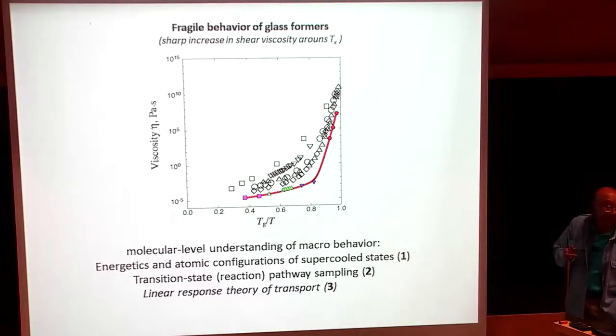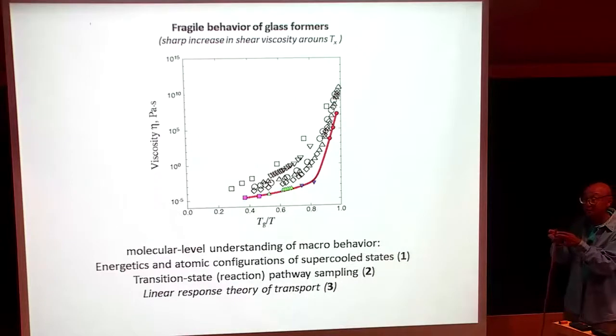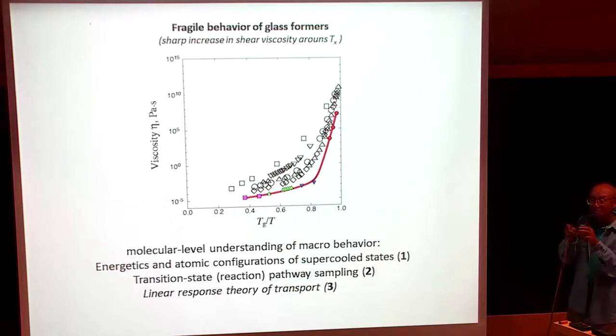People who do scattering experiments will say, well, I don't necessarily measure g(r), although you can get it out of the data. I don't measure viscosity. I measure a diffraction pattern. I can take a liquid and measure its diffraction pattern, and I see rings, the so-called Debye-Scherrer rings. If I start to quench this liquid, at some point the liquid crystallizes, and I know that happens because I see black spots. So if you do a diffraction measurement, you have another way of defining whether you have a crystal or a glass. If you have diffuse rings, or you have black spots. But the problem is that when they do this kind of experiment, they see both. They see the rings, and inside the rings they see remnants. So it's not one or the other. It's not a sharp transition. So that's why there's all this discussion.